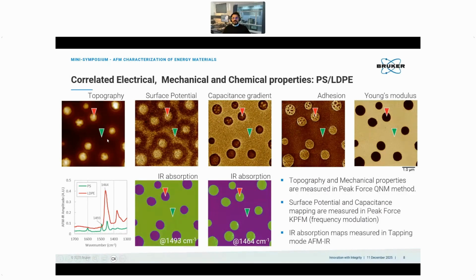Now, the thing is, with the methods available, and again, I thank you for answering the questions in the questionnaires about that. We can measure, for example, the surface potential using peak force KPFM. And if we do it in the frequency modulation, so that's basically the peak force KPFM mode, if you have it or if you are interested in it, we are able to measure in parallel the capacitance gradient variations. And this is something that I published 2 years ago. You can find it. It shows you how we can measure the capacitance variations.